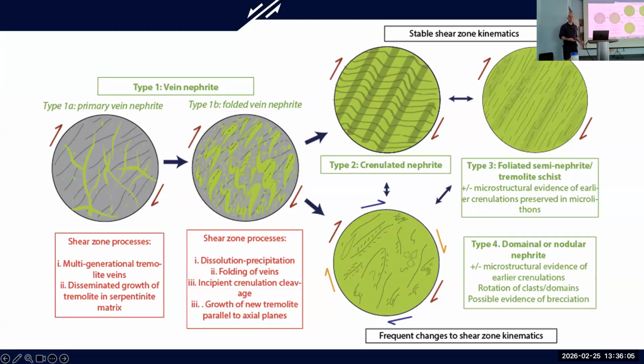And this condition of constant change is in fact why nephrite is relatively rare in the world. It's one of the reasons it's valued. In most shear zones, if you go and find some kind of nephritic tremolite, it's very liable to have sustained, or at least the rock that you see, the last thing that happened to it is sustained some kind of stable kinematics that turns it into a schist. So the vast majority of the world's nephrite is schistose, but under the right conditions, you get this domainal fabric, and that's ultimately what characterizes nephrite jade.